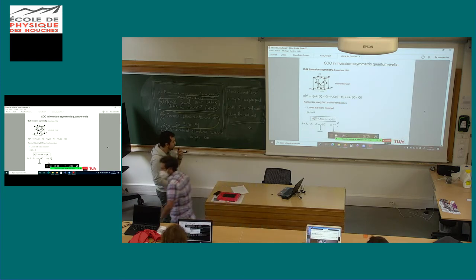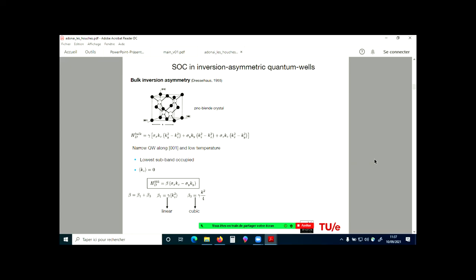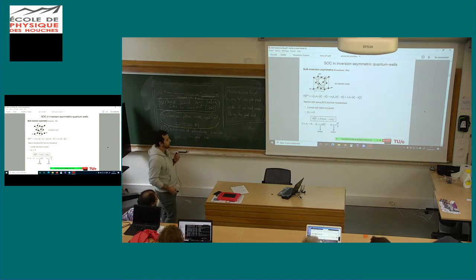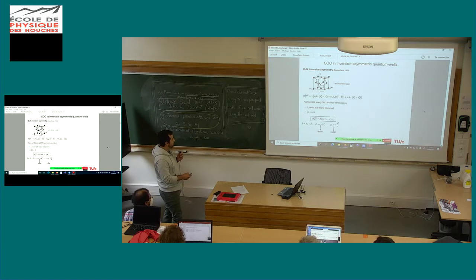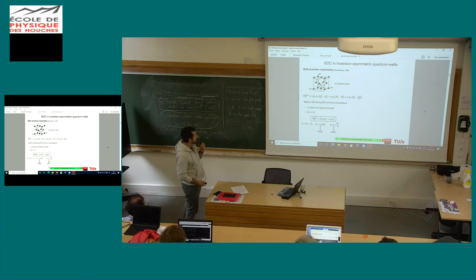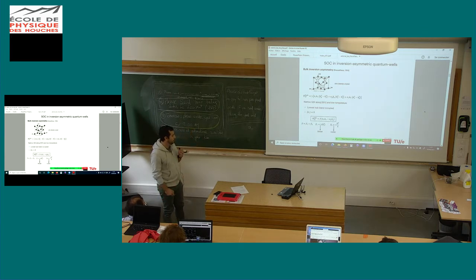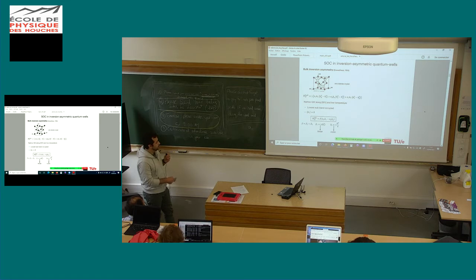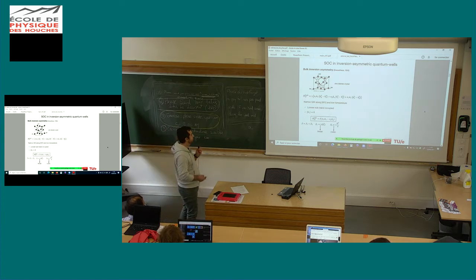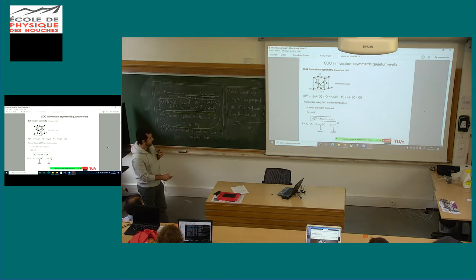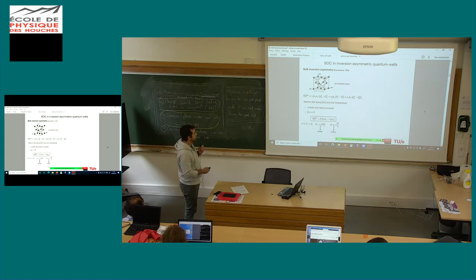Here we assume that just the lowest subband of the quantum well is occupied with conduction electrons, and moreover we can substitute the momentum by its average value. The first order in kz is zero because of confinement, and we end up with a simple expression for the Dresselhaus term in this specific growth direction. This expression changes, of course, if you do a rotation in k and spin, giving different expressions for different growth directions of the quantum well. Basically there are two terms: one that's linear in k, called beta 1, and another contribution that's cubic in k, which I'm going to neglect in this model, since it usually has a lower value than the first one.